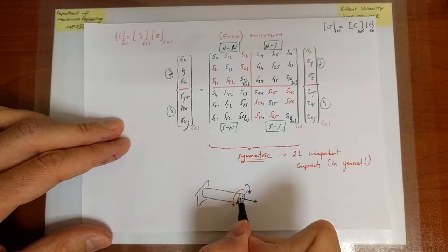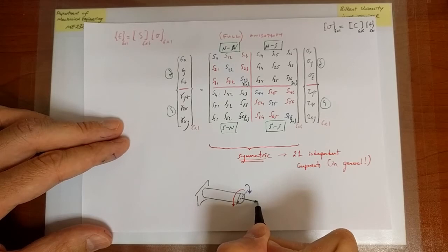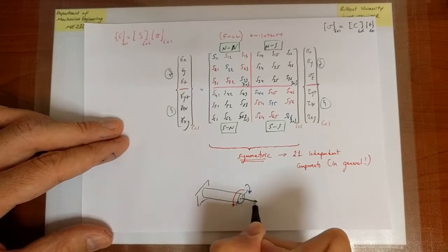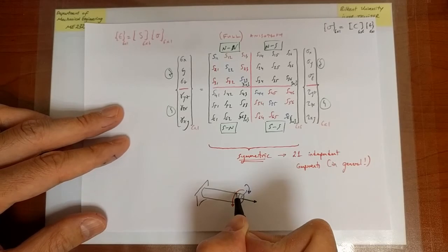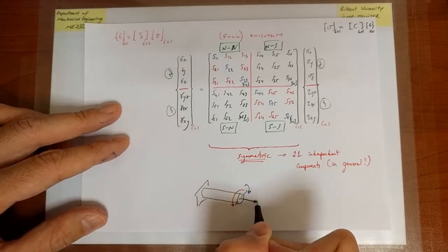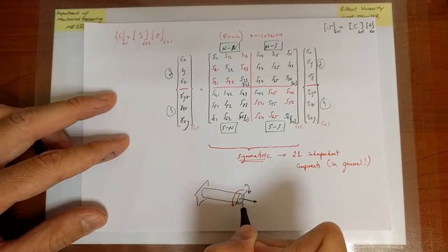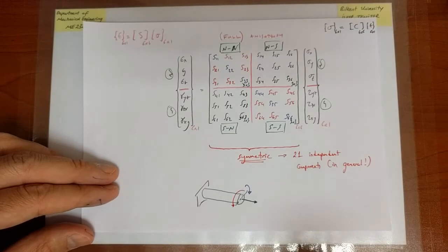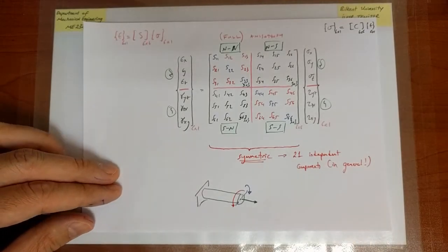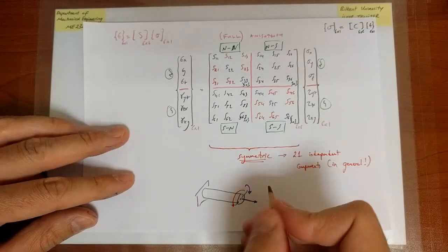I pull on the elastic cylinder. So when I pull in that direction, it extends in that direction, and then I slowly reduce the amount of the load. So I don't push, I don't need to push, I just release the amount of force I apply. It's always in that direction, it just goes back to zero from a positive value. But now the motion is in the reverse direction, so the work that is done is negative now when I unload. So loading is positive work, unloading is negative work, and then the net work should be zero. That's your expectation. Why? Because that is ultimately defining your, or fitting your definition of an elastic material behavior.